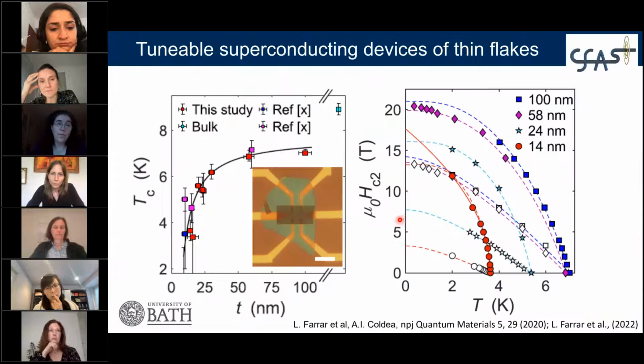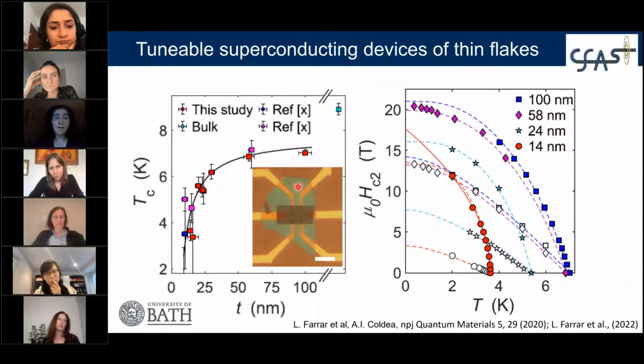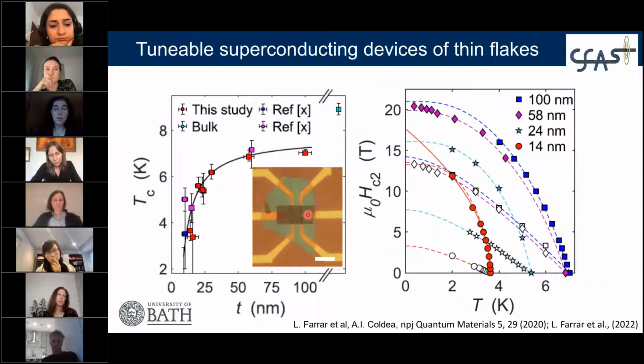And from fundamental research, we move towards how we can implement this type of materials also in devices. Because these iron chalcogenides have van der Waals bonds, they can be exfoliated in thin flake devices. Here we have explored how superconductivity varies with the thickness of the flakes. We noticed that in thin flakes, superconductivity is suppressed, as opposed to a monolayer case on a substrate, where superconductivity is strongly enhanced.